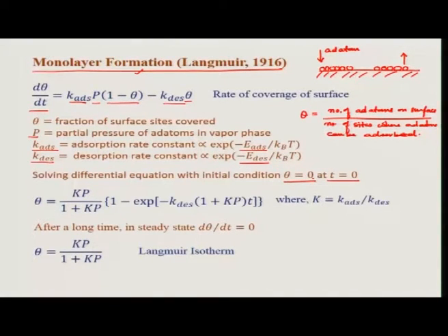So, theta was 0. If we solve this differential equation with this initial condition, we will get this expression for theta, which describes how the fractional coverage will change with time. Okay. So, this is time, and this factor k is just the ratio of adsorption to desorption rate constants. Okay.